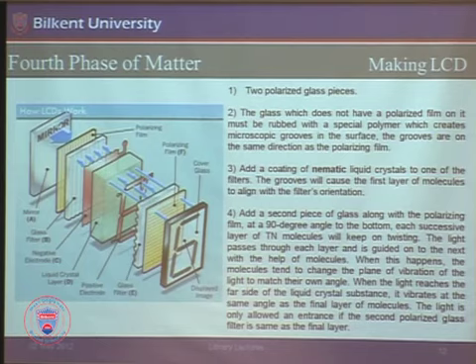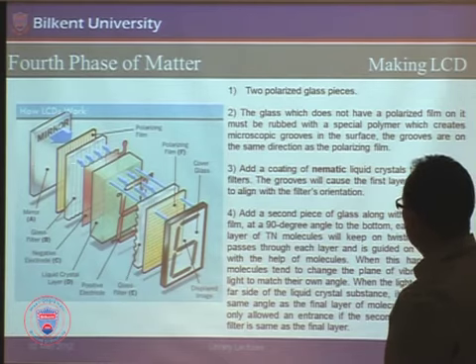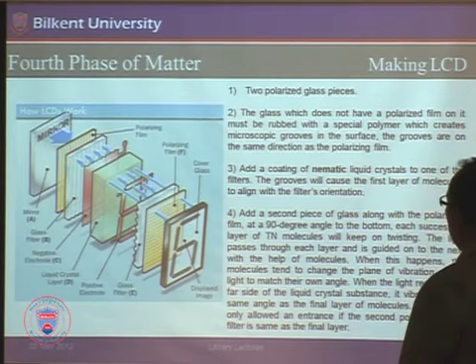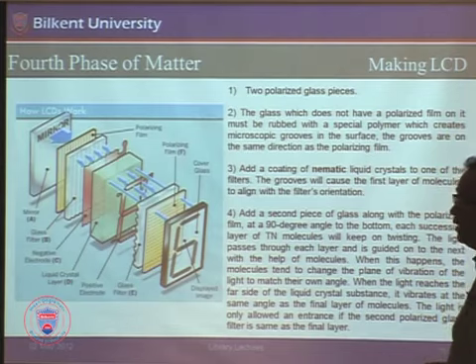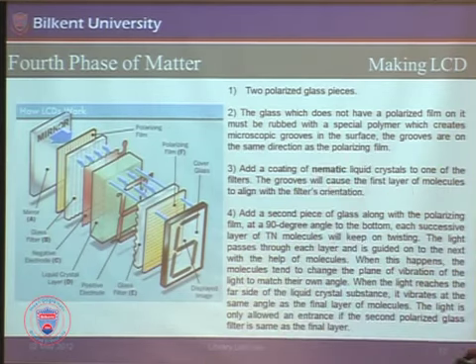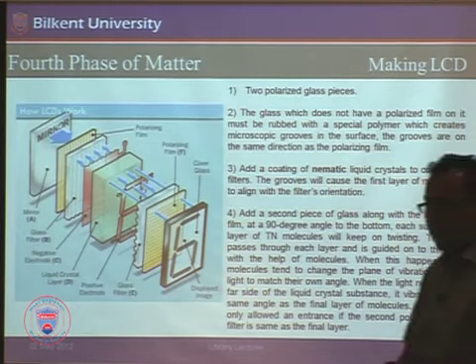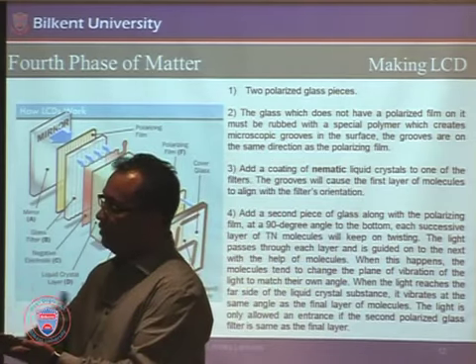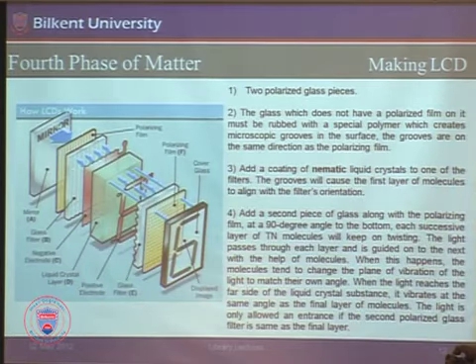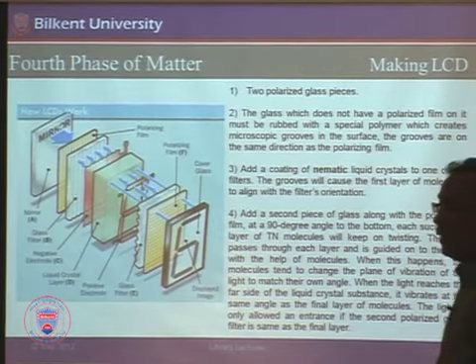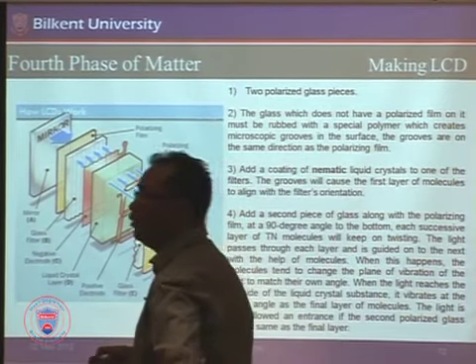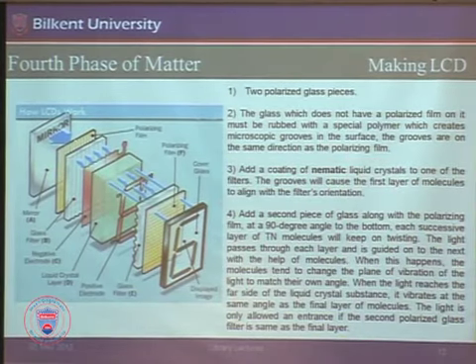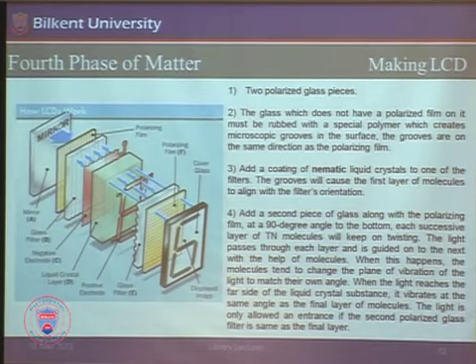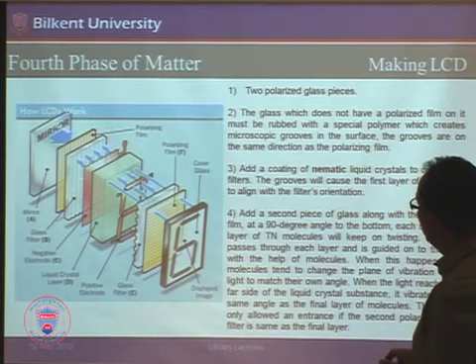This is one single pixel. You have a reflective mirror. This is just a mirror, that's not really important. You have the polarizer, like in the microscope. These yellow lines show the direction of light coming from this polarizer. And you have a glass, and this glass is special, not regular glass. It is rubbed with a polymer, and this rubbing direction is important. This rubbing direction is parallel to this polarizer. When you put the liquid crystal in, this is the first step: how the first molecule aligns will determine the first layer of this liquid crystal. And there is a thin layer of an electrode. This is the negative pole when you apply the voltage. And you have the liquid crystal here, and you have the second electrode.